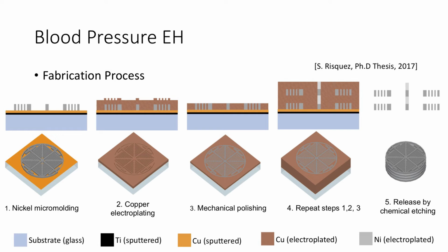You just have to take care of the alignments if you want the system to be well connected, and you repeat those steps as much as you can. And once you're bored about that, you stop, and you release the nickel microstructure by chemical etching. So it was a really seducing way to build complex systems. In practice, it's a little bit complicated. All the steps are complicated.